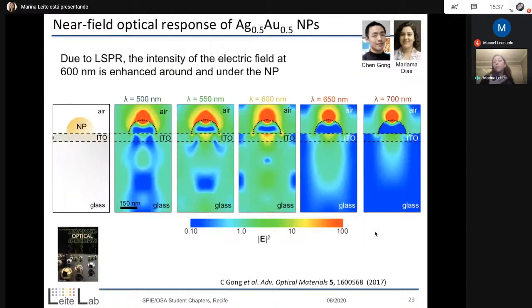And then if you want to have a full picture of what's going on, instead of looking at a plane monitor only, you can also look at a cross-section monitor. And that's what we're showing here. I think it's even more clear. So at 600 nanometers, when we're at resonance, you can see all these bright spots around the particles, and also on top, really due to the localized surface plasmon resonance. So I think that's very helpful, specifically those underneath the particles. So we do have this field enhancement that we desire so much. And we could do a few things to optimize this field enhancement, like the size of the particle and geometry and all that kind of stuff.